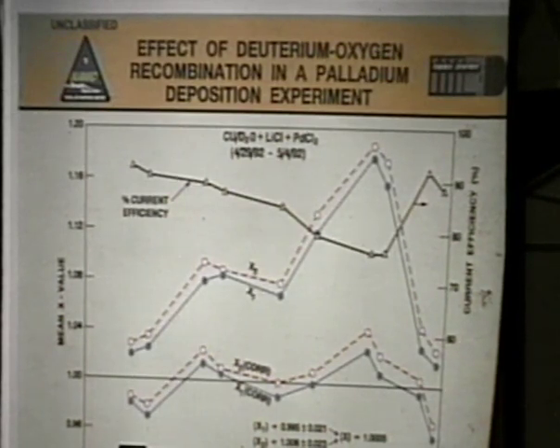This is the current efficiency that we measure by measuring the gases coming off. And you see it's always less than 100% in this type of experiment. This is the apparent excess heat. And it looks like we had excess heat if you don't consider the recombination. But we know the recombination because we measure it. So if you correct for this recombination, it corrects back to here. And you can see we're back to break even. Heat in, heat out equals heat in.